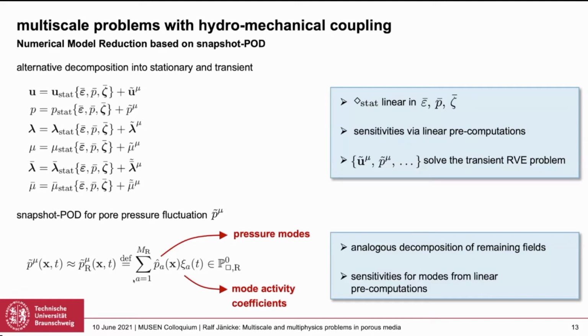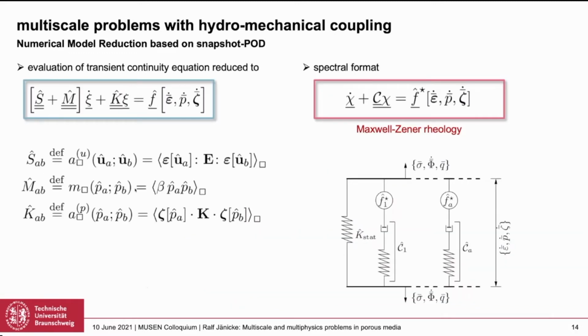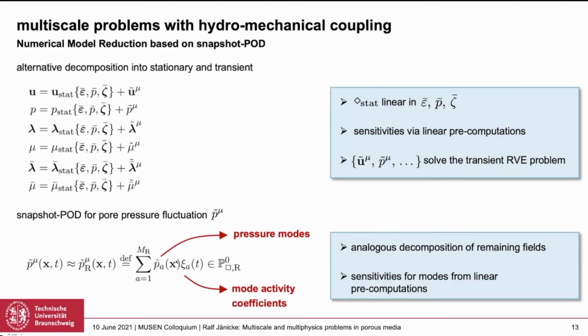The good thing is that all quantities depending on these pressure modes can again be pre-computed. We call them sensitivities, which can be pre-computed after the training. That means they are out of the online phase. Okay, but now we have to see what happens to the equations. First of all, we assume that a similar decomposition can be done for all quantities: we are interested in displacement, and the Lagrange multiplier, meaning the fluxes. Then we put everything into the continuity equation. We do some massage of this equation, and the beauty is that what comes out is basically an evolution equation for those mode activity coefficients, which are the unknowns in this transient problem.